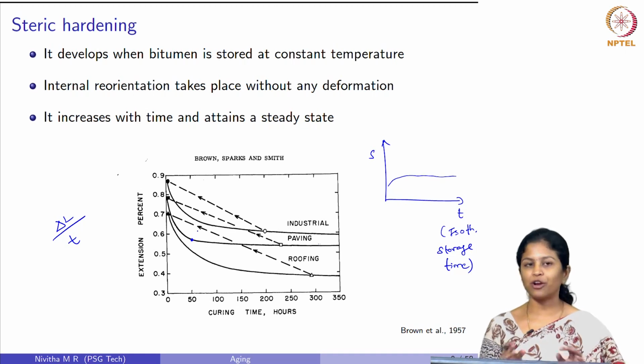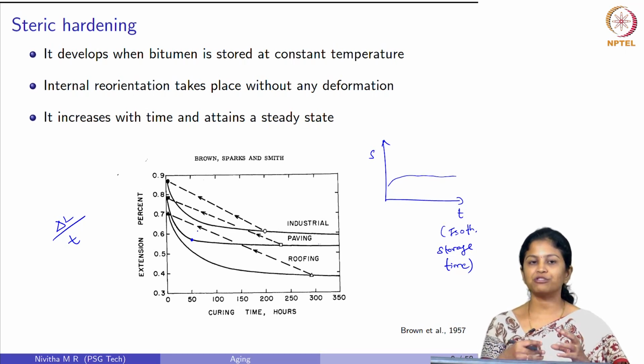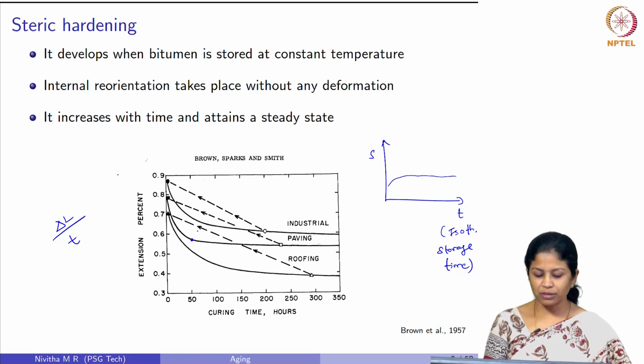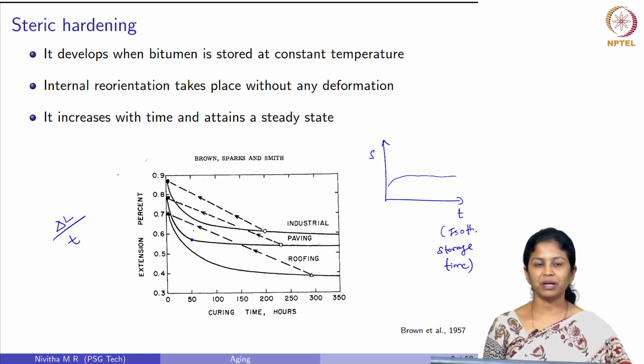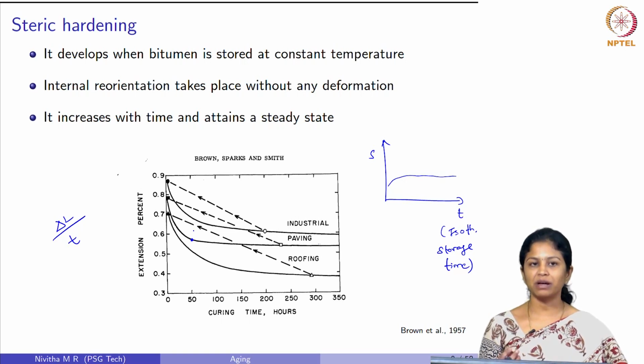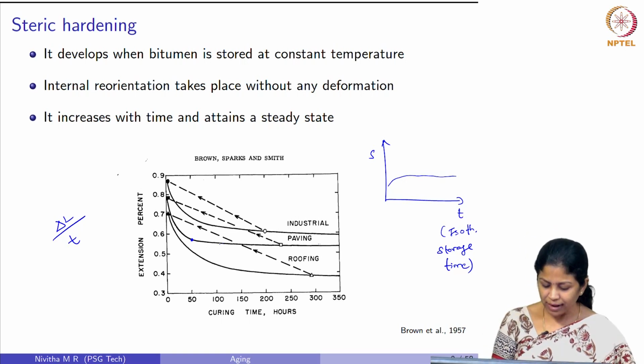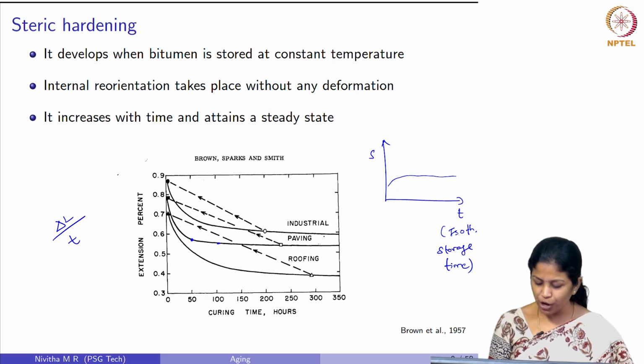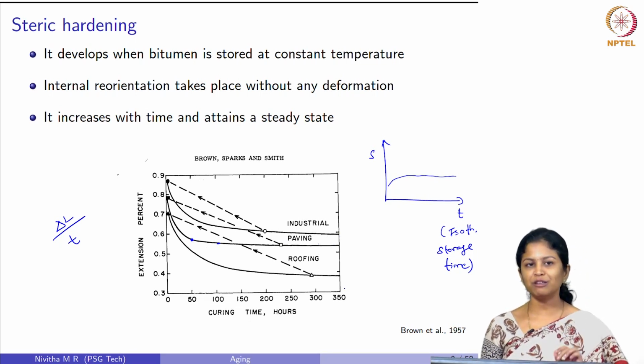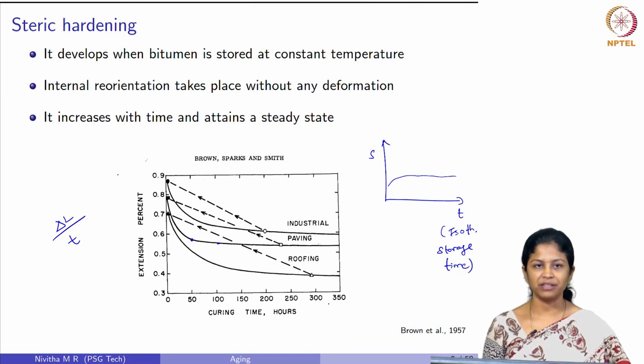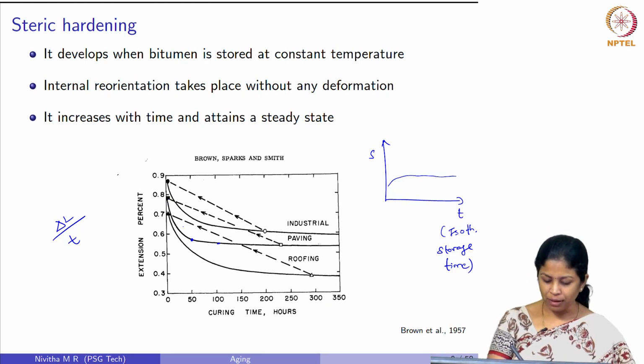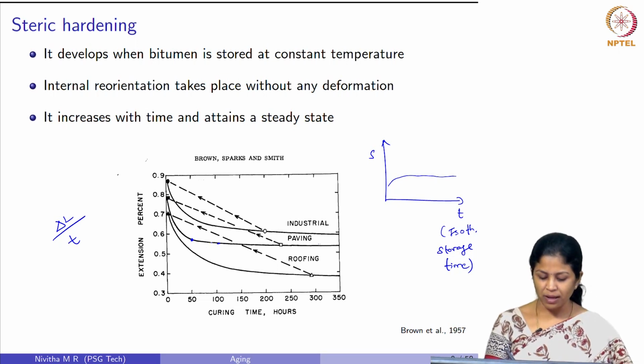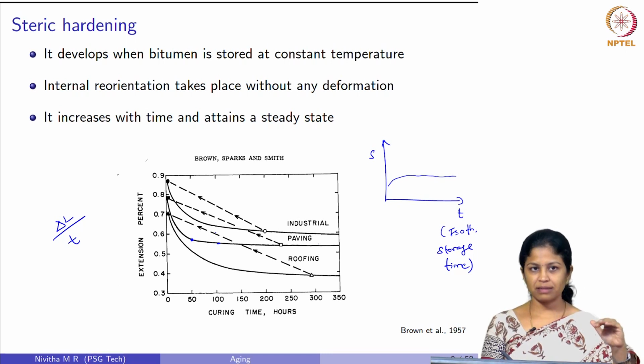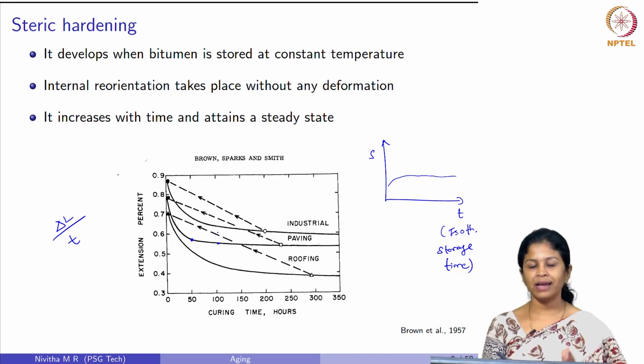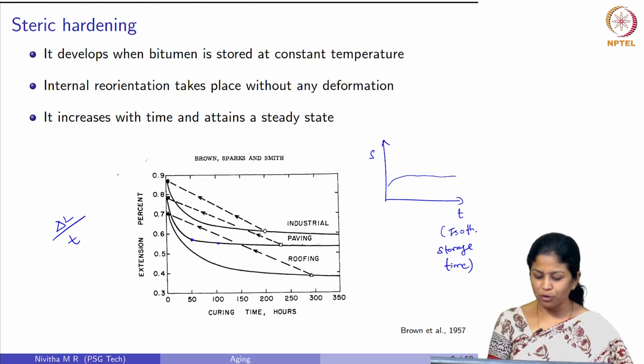It is the same material, we are not doing anything to this material except that we are storing it at constant temperature. So, this storing has reduced the extension percentage, which means that the material has become harder. And after 100 hours there is a very small reduction, and beyond 100 hours we can see there is very negligible reduction in extension percentage. So, from the 0th time up to some period between 60 or 70 hours, the material has hardened drastically, and beyond that point of time it has almost stabilized, right. So, this is in the case of paving grade bitumen.